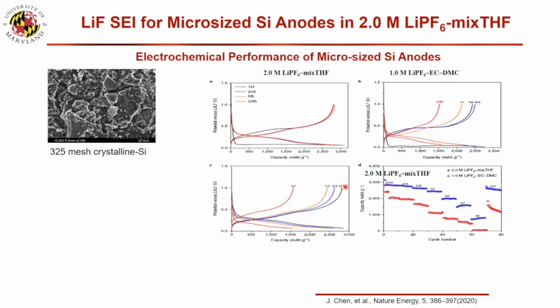And we also show high rate, because lithium fluoride is always believed to have a very low lithium conductivity, and maybe they suffer from poor rate capability. But I need to mention that the lithium fluoride is so thin overall, so the ESR is really, really small. So they even increased the rate capability. So this is the rate performance. We can reach 3C and 5C. At 5C, we still got the high capacity. But the red one is traditional electrolytes.